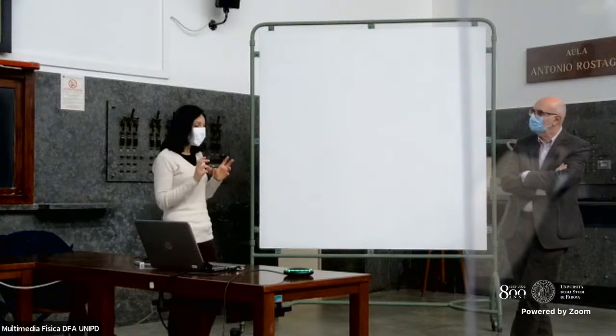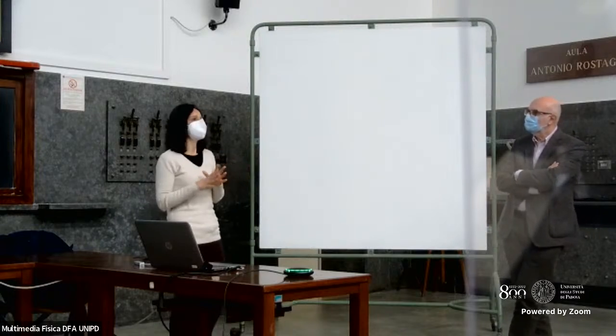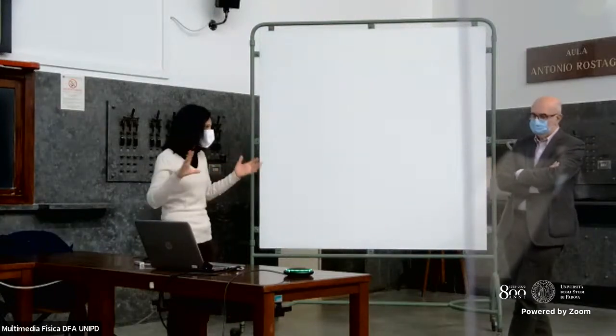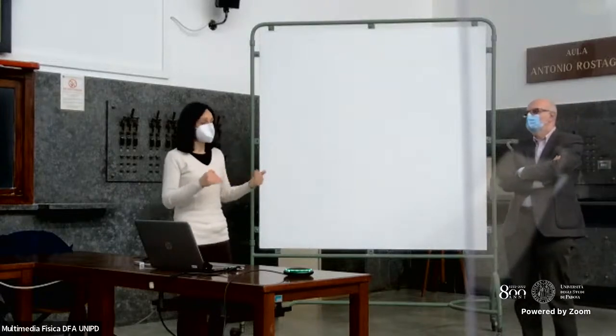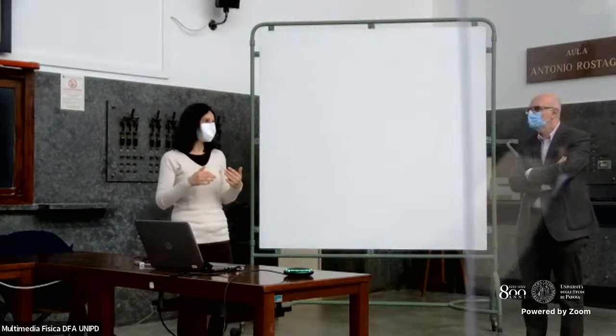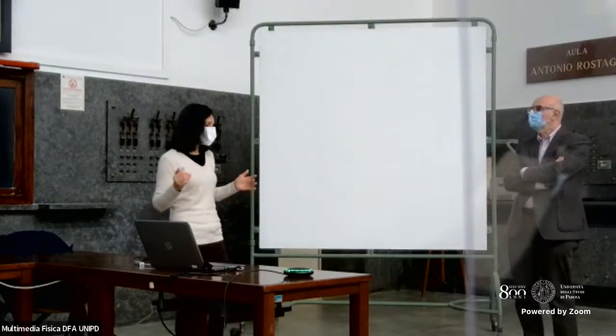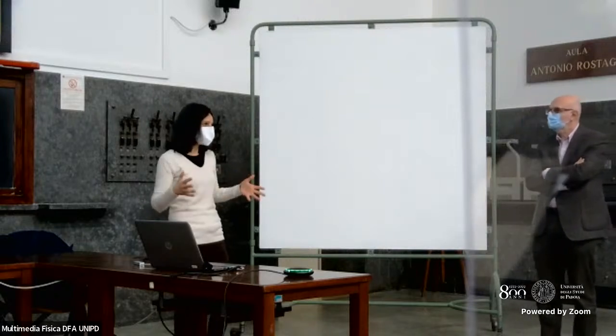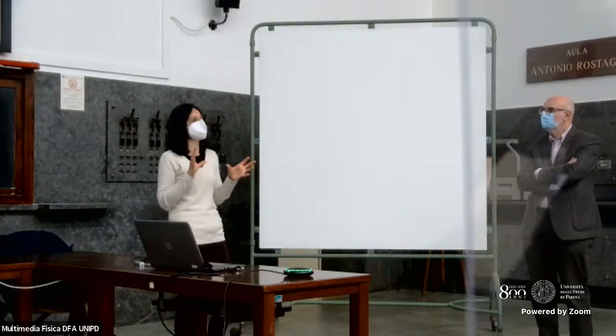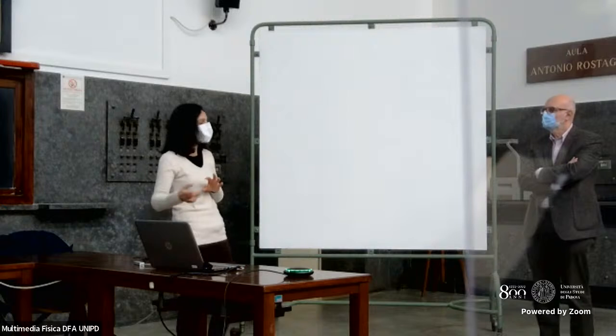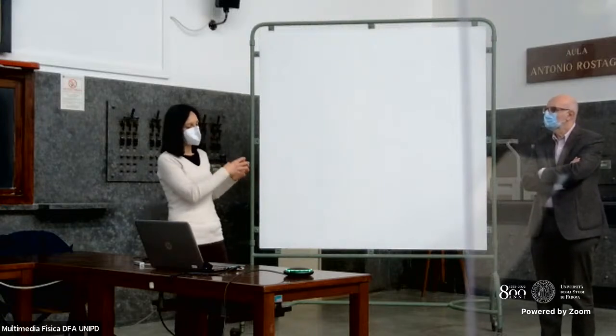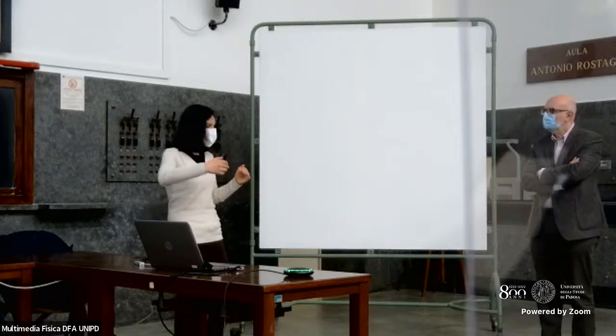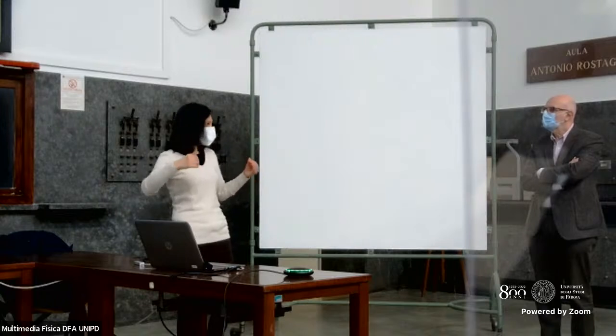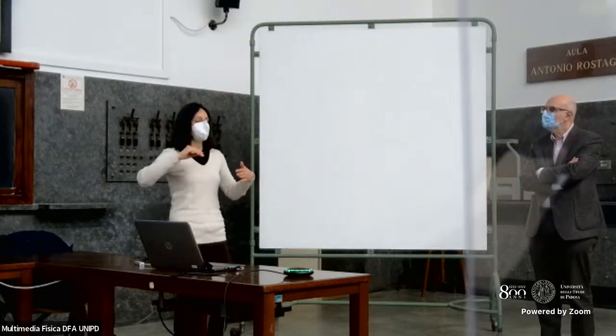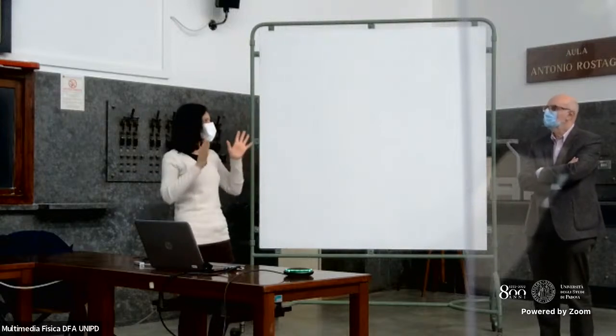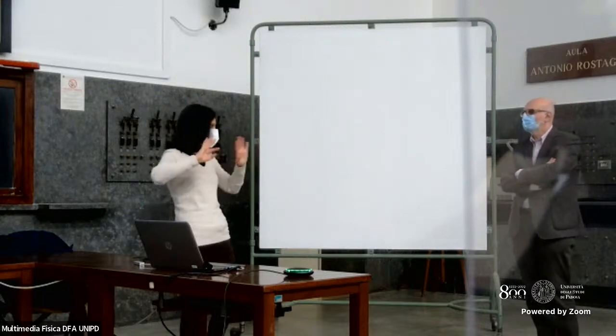It is not totally easy to use some functional polymers such as piezoelectric polymers with this equipment for large scale applications because of several issues, and because the technology that is much more widespread for large area applications is a little bit different. It's not needle based as the one that I showed before. It is called free surface, where you flow the solution within big tubes which are drilled with holes. You apply the field to the tubes, and there is a collector, and fibers are spun outside like this. So you have many jets, not just one jet.